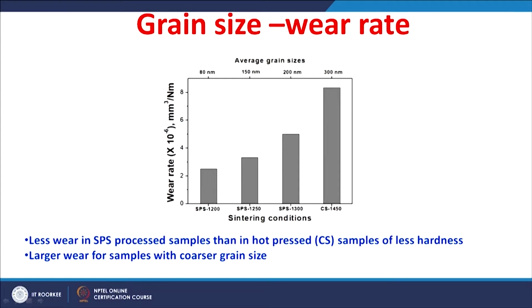You can see the wear rate is very low for the spark plasma sintered ceramics compared to the conventionally sintered ones. For comparison purposes, these same ceramics with 3% yttria stabilized zirconia were also sintered by hot pressing at 1450 Celsius. So, you can see the higher wear rate obtained for the conventionally sintered ceramic, whereas the lower wear is obtained for the spark plasma sintered ceramics.